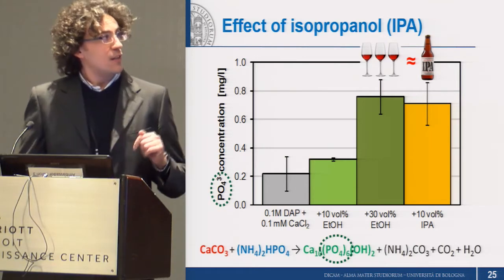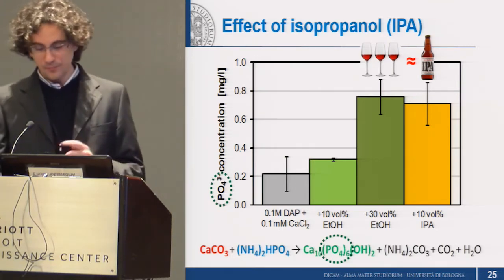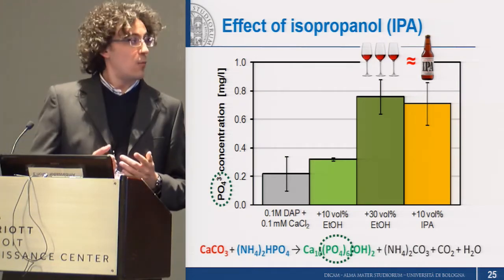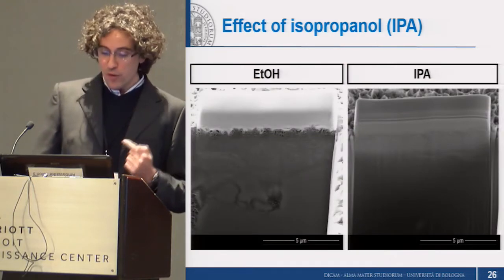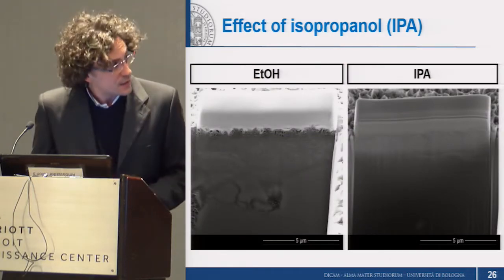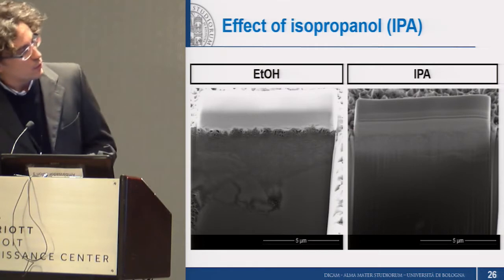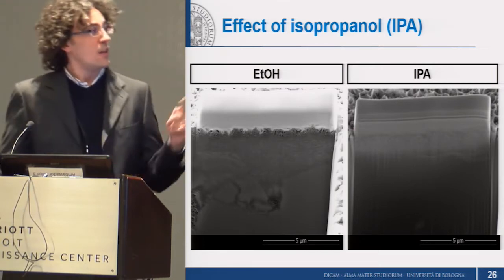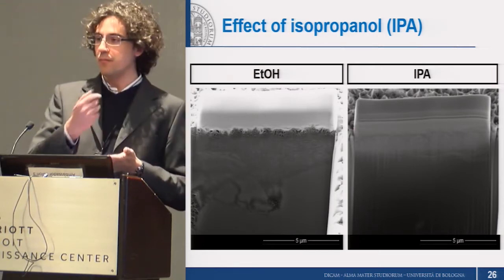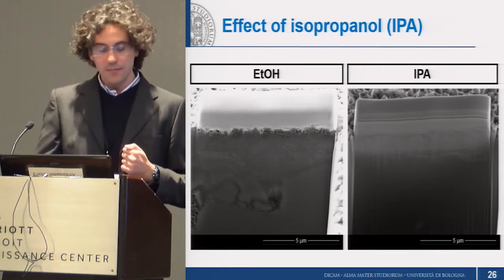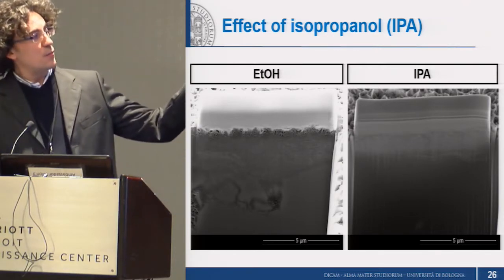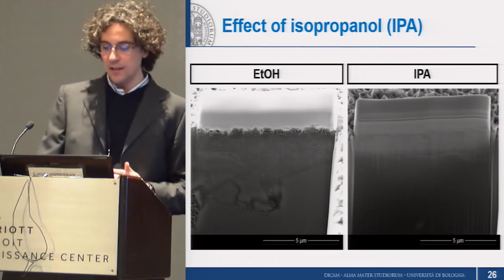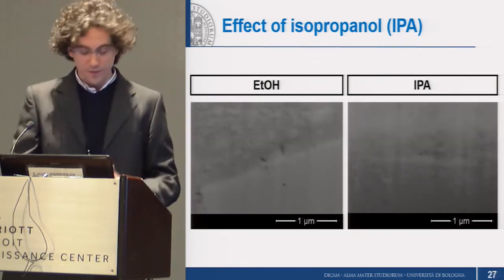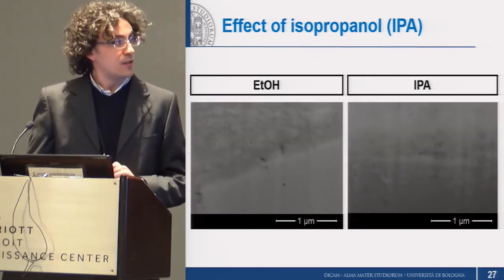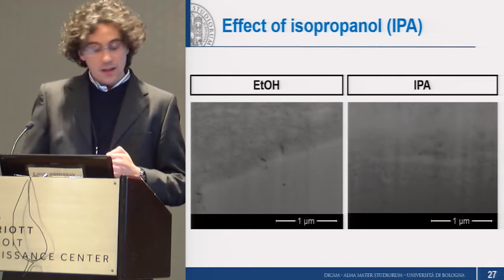So we moved on to testing IPA as a solvent to be added to our solution, and we found out that the density, I'm not sure if it's possible to appreciate from these pictures, but anyway, the coating that forms is much denser, and also at the interface between calcite and the new phases, it's basically quite hard to identify a sharp interface, which is good.